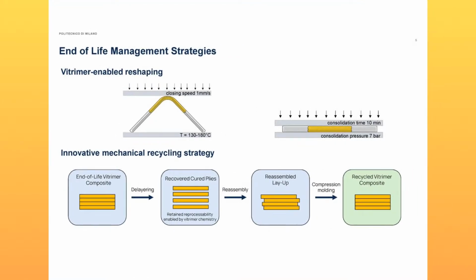The second big field where we are working is basically the end-of-life management strategies. Typically, thermoset matrix composites are recycled in a two-step phase. A first phase of fiber reclamation, where we try to degrade the matrix and extract the fiber. Of course, proceeding in this way, the value of the matrix is lost. Vitrimers are able to be simply reshaped.